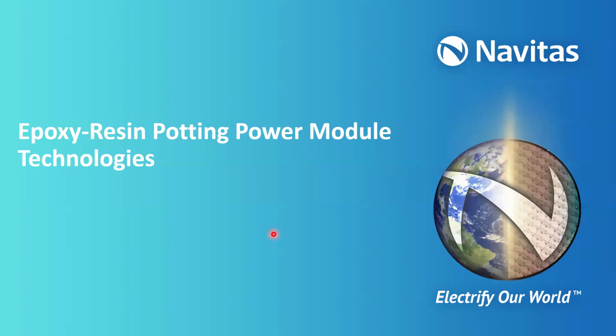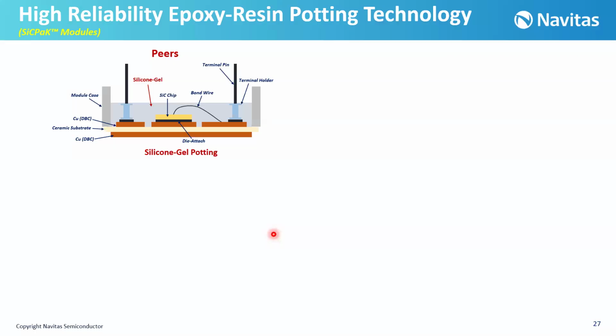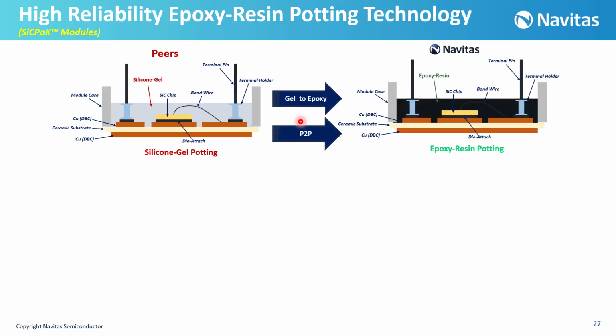Now let's talk about the epoxy resin potting power module technologies that we developed in Navitas. First of all, let's look at the traditional modules. In these traditional modules, we have the DBC, which is the copper ceramic substrate, and then we have the silicon carbide chip, which is bonded with the wires, and we have die attached over the DBC. And then after that, we are pouring the silicone gel in order to have this module. In Navitas, we developed a technology, and in this technology, we replaced the silicone gel with epoxy resin.